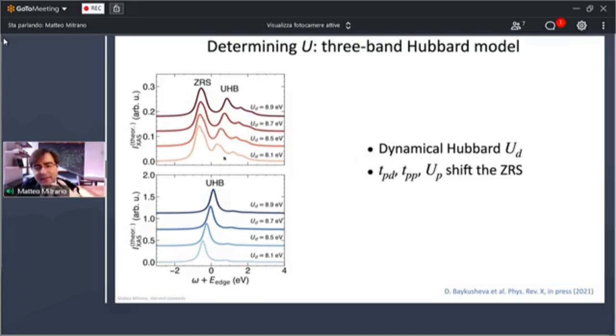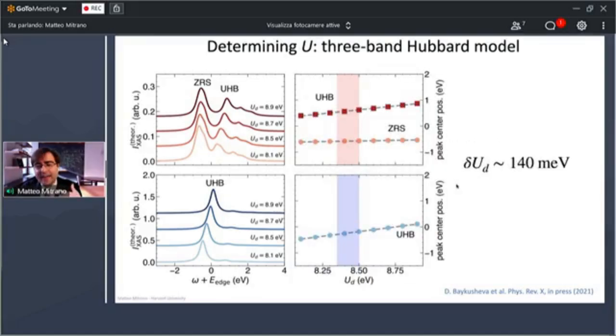The punchline of this analysis is that if we systematically vary all the parameters of the 3-band Hubbard model, we discover that the only parameter that actually reproduces our observation of a fixed Zhang-Rice singlet and a moving upper Hubbard band is a dynamical change to the on-site Hubbard U. That is essentially the energy cost of putting two electrons onto one single copper orbital. Any other parameter would shift the Zhang-Rice singlet. So we are dynamically altering the band structure. And the extent to which we are doing it, by looking at the slopes of these dependencies, is approximately a change of 140 meV. That is actually a sizable change for a modification of an electronic interaction parameter in these materials.